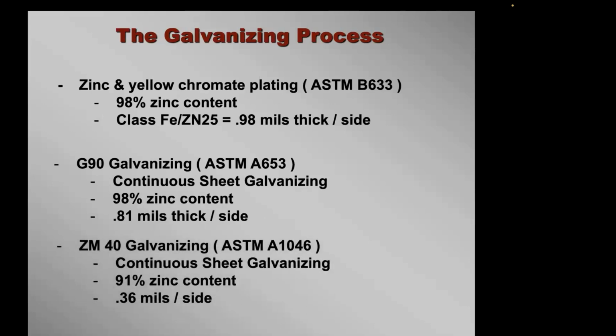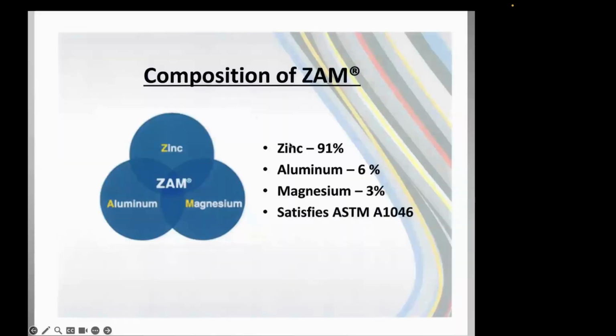And your G40 or ZAM40, the ZM40, is only 91% zinc. The A that was in there before stands for aluminum. They replaced some zinc with aluminum, and supposedly that makes it last longer than hot dip galvanizing in a brine tank test. But when I talked to the engineers at the American Galvanizing Association, they said the brine tank test is not relatable for hours in service at all. They have their own method of measuring, and I'll show you that in a minute, but that's only 0.36 mils per side. So here's the ZAM, like I was telling you.